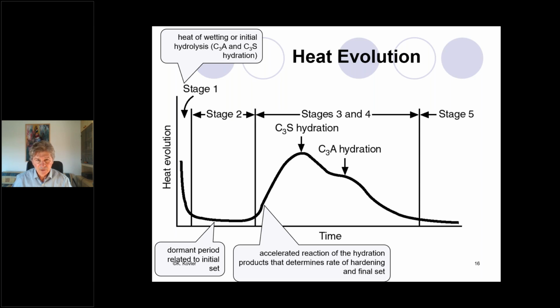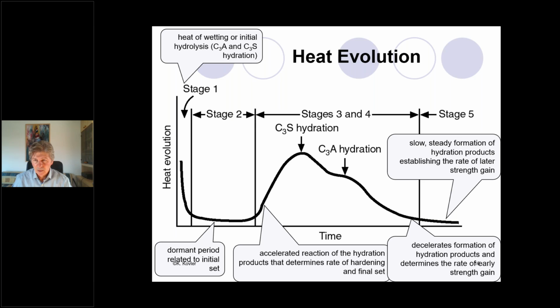Stages 3 and 4 indicate the C3S, alite hydration, the main mineral usually in Portland cement, and C3A also. And deceleration, when the formation of hydration products is decelerating. And this phase is determining the rate of early strength gain. And then slowly, the hydration products are formed and the strength increases.